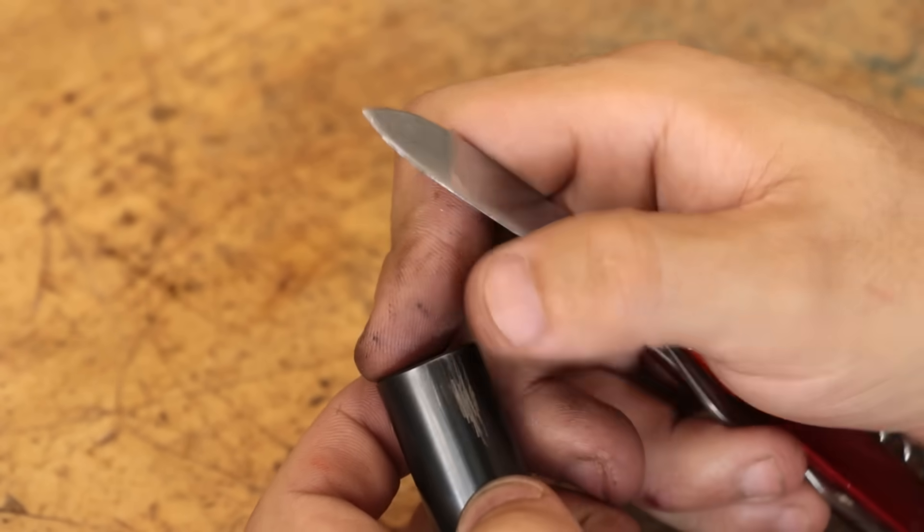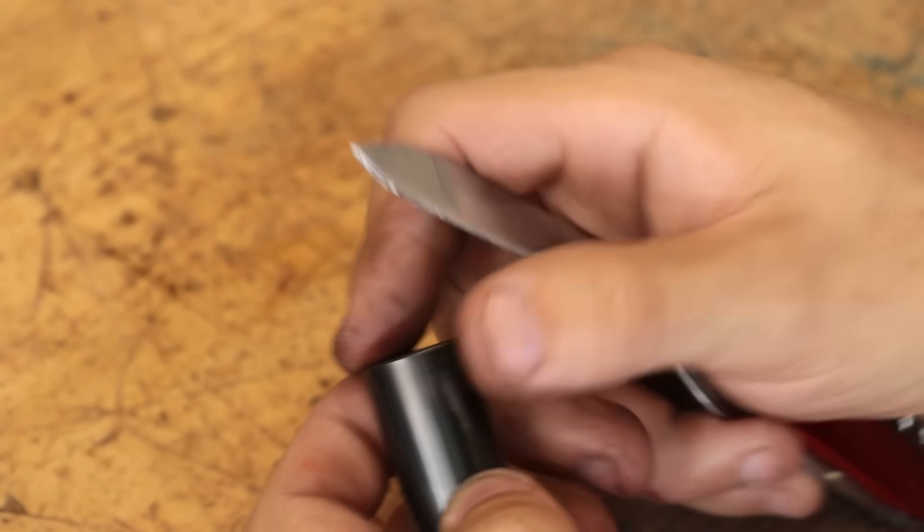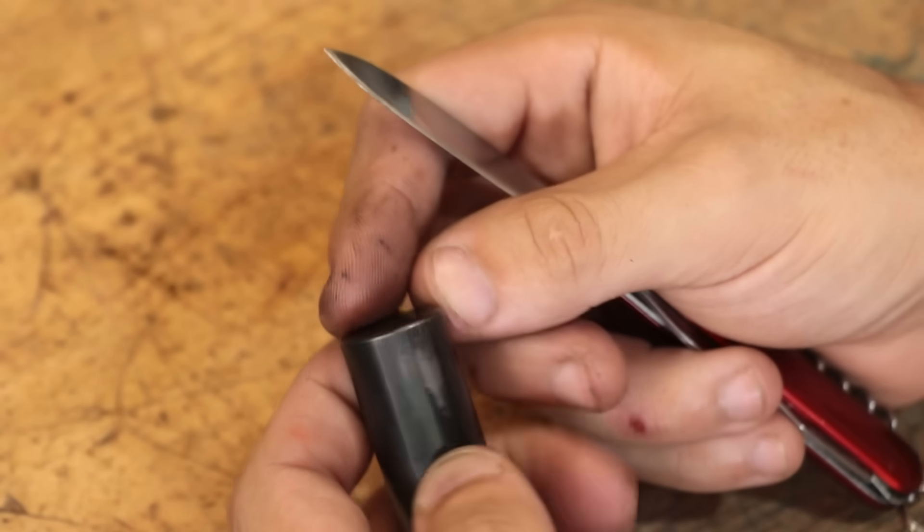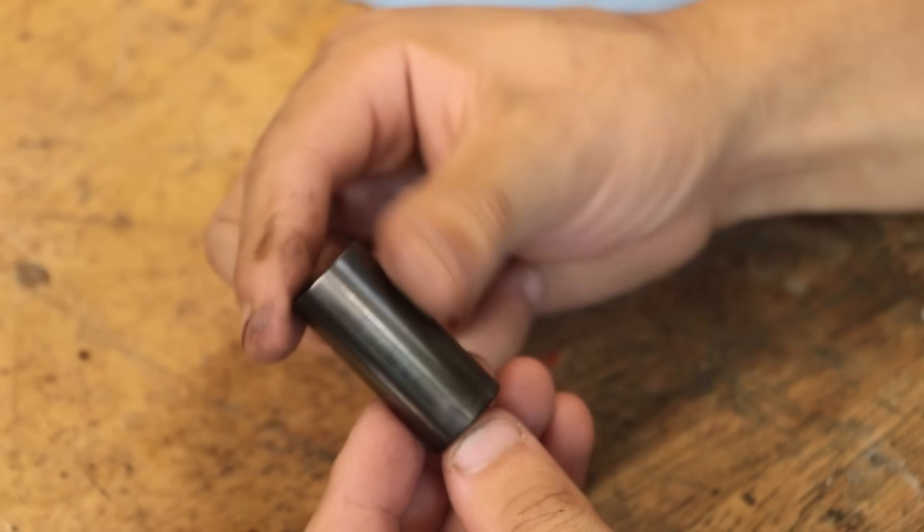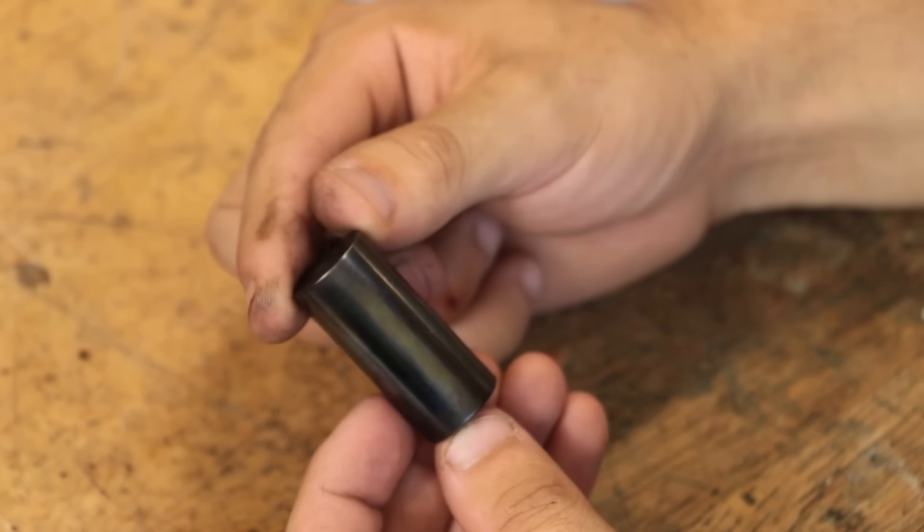I also think it's worth pointing out that this stuff technically isn't blue if you go by the traditional definition, where bluing uses a black iron oxide to make the coating. From what I've read, this stuff here is selenium dioxide which binds to the surface of the steel and leaves this porous black finish which can absorb oil.